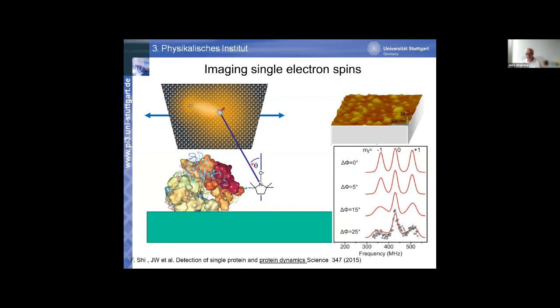This angle theta is not isotropically distributed, because of steric hindrance this molecule can only take certain orientations. Essentially what you see here is a histogram of these possible orientations. It is encoded here in the interaction frequency. We were doing these experiments, measuring this interaction histogram, and then fitting it to different models of how this electron spin can move. The best fit is given by this red curve.